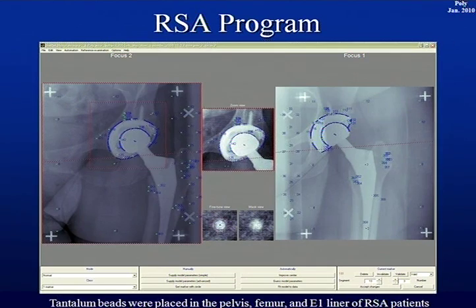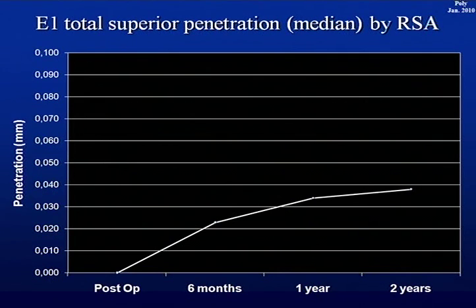But for the rest, you put in tantalum markers here. Then you can measure how the cup is moving. You put tantalum markers into the polyethylene. Use the center of the head, and you can read how the poly deforms alternatively wears. And you do the same for the stem here to have control of all factors as such. And you put all that into a software package developed here in Sweden, and you get results like this out.